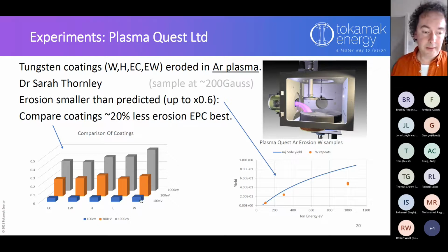We've compared the coatings again. You'll see, so this run here, these blue squares, L is the additive manufacture one done by LAS, and you'll see it's basically the same as plain tungsten and these different coatings. The orange ones are at different energies. Again, they vary up and down quite a bit, but the coatings we find are all very similar. Additive manufacture behaves pretty similarly to thermal spray and chemical vapor deposition coatings, and in general they're a little bit better. So the sputter yield is a little bit less than our tungsten samples, just normal plain tungsten.